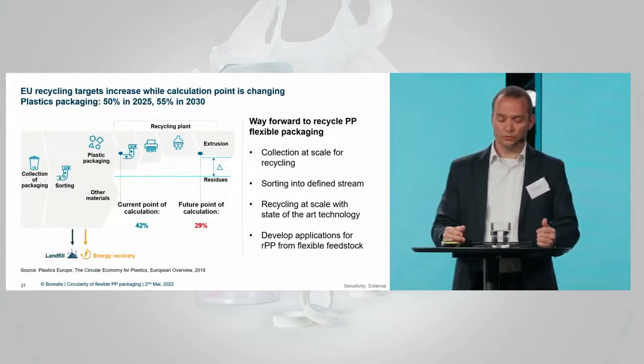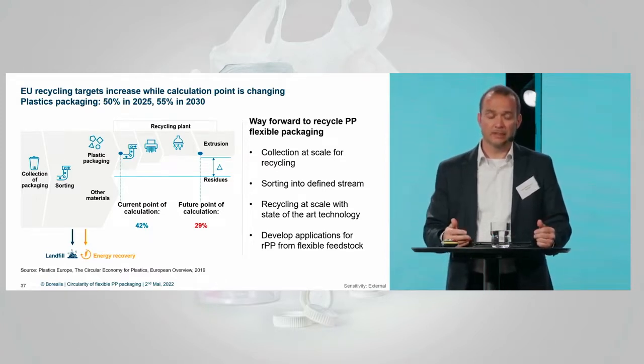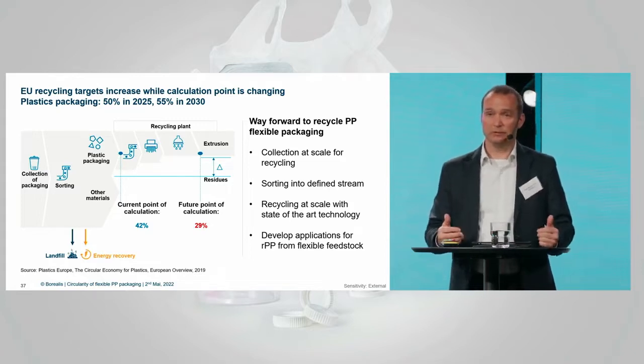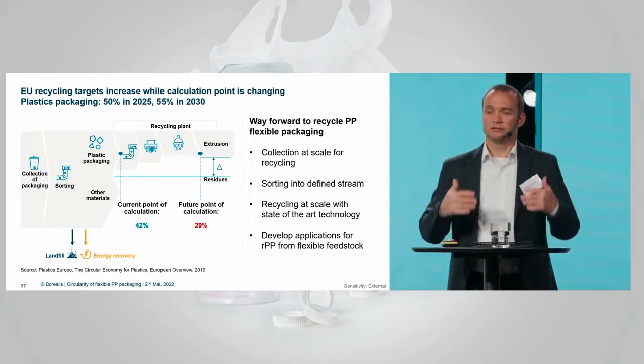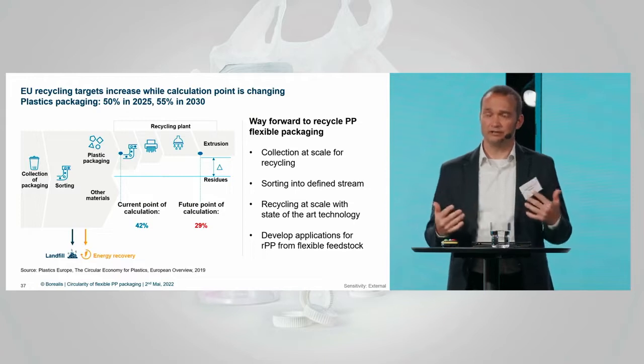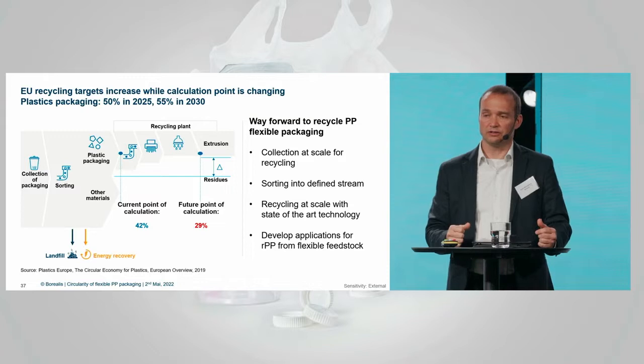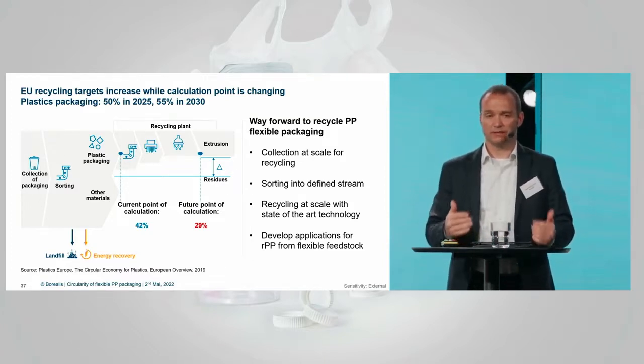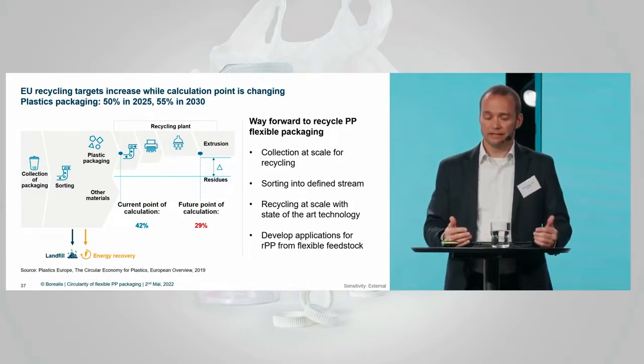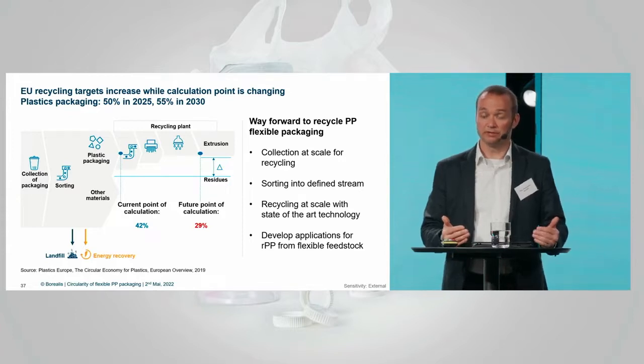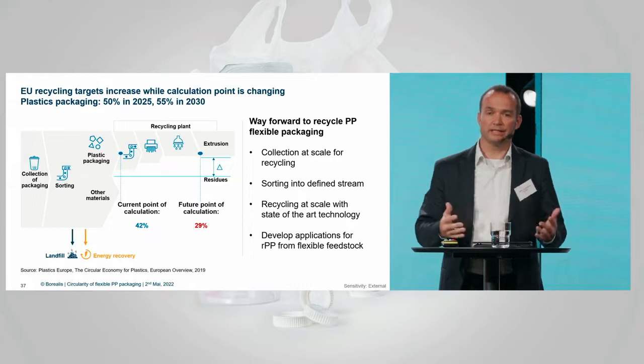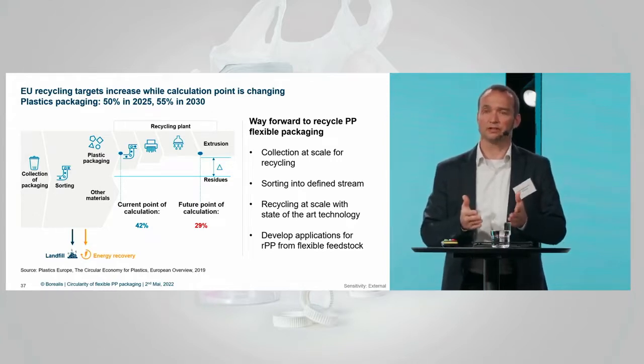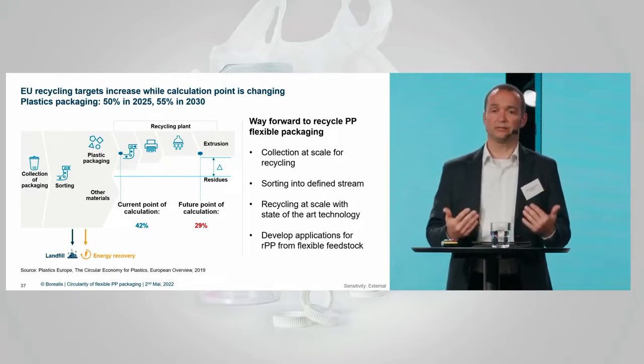So I want to explain why we believe that this is the right way forward. We have been making a test at Borealis where we looked at what happens if we recycle flexible packaging today, respectively PP flex packaging. You can find it, depending on the region, of course, in some mixed fractions, mixed with other polyolefins and other flexible packaging. If you put this into a standard or conventional recycling process, with not too much effort in sorting, purifying and cold washing, then the result, respectively the quality, is quite limited. It's relatively poor quality, and such material can be used only in some lower end applications. So it's narrowing down the use of this recycled material. And that does not help us to increase the recycling rate, which at the end we also want.